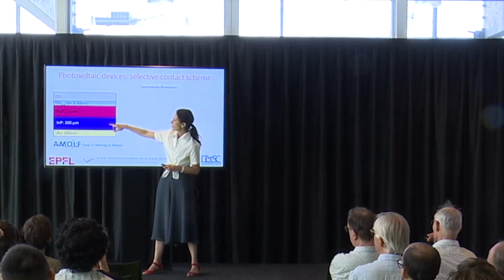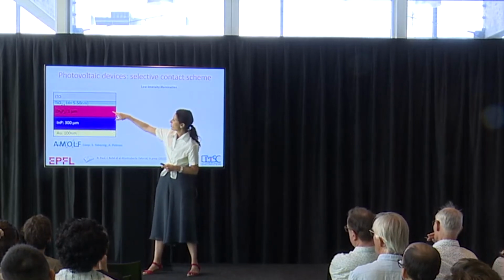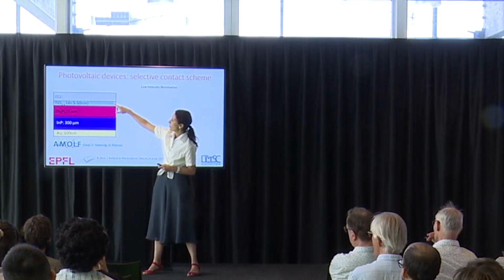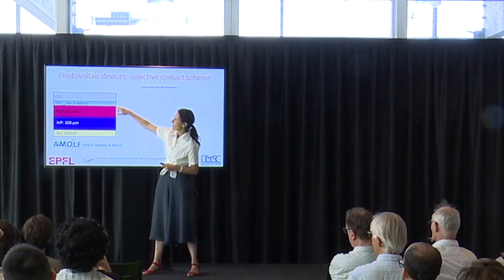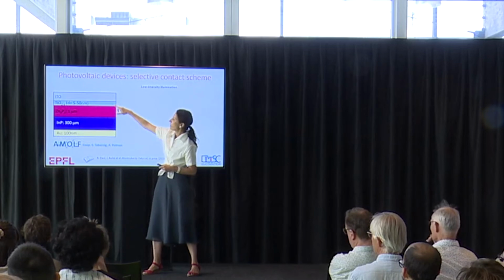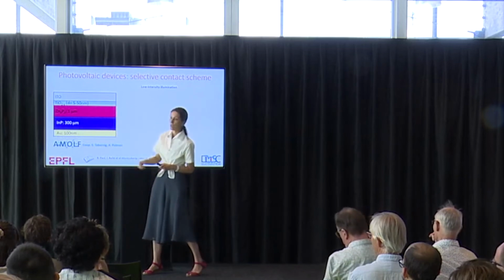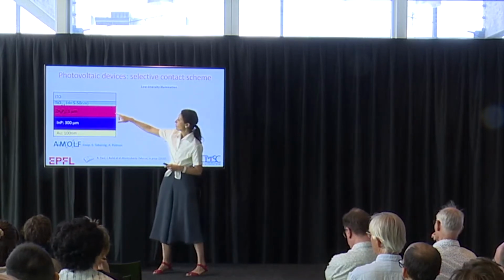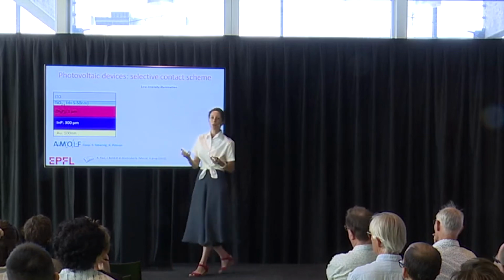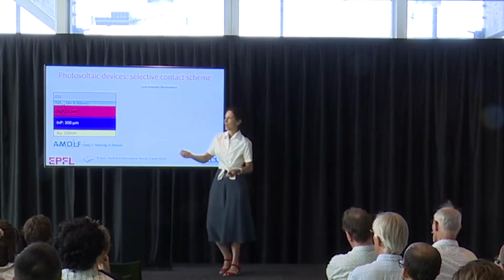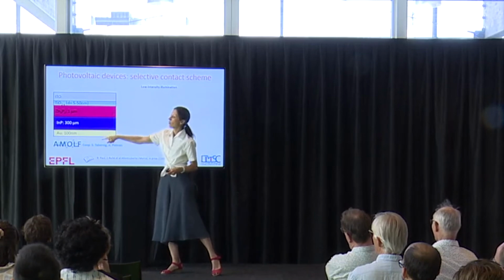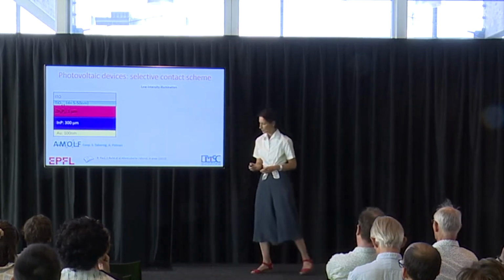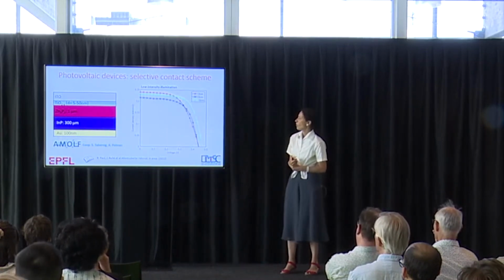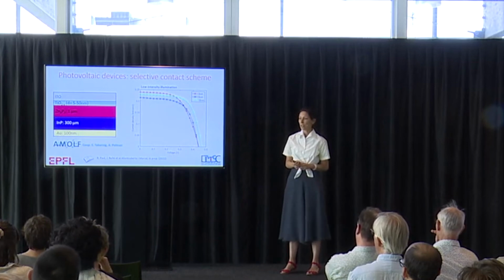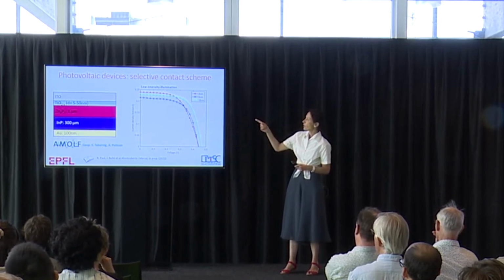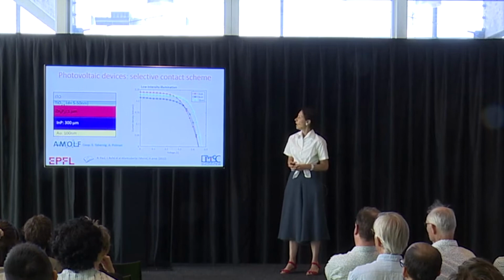When we use non-doped indium phosphide as a substrate, we have most of the absorption here. We use titanium dioxide as an electron selective contact, then a transparent contact on top, and in the back we have gold. So in principle, you can absorb here, create electron-hole pairs, and they wander around. Electrons will go here, and holes will be collected in the back. And these are one of the first device characteristics that we show. So this is under low intensity illumination.